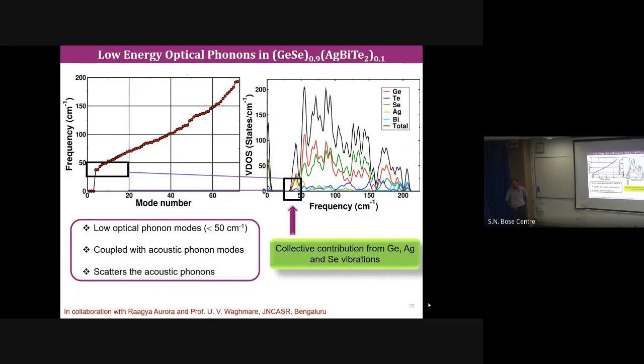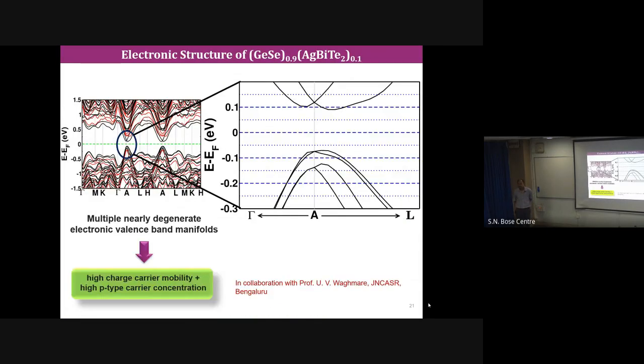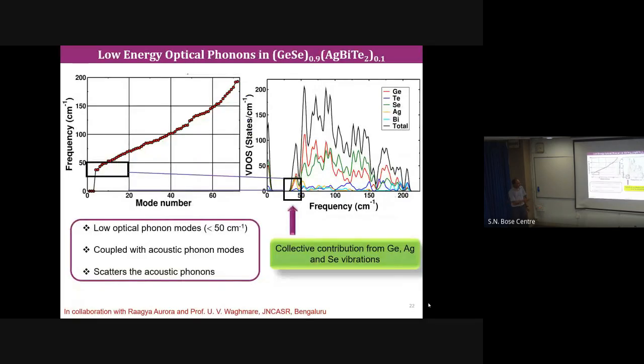Your system is disordered, right? What kind of structure is going? So basically, what you do, you calculate based on the ordered structure, an energy-minimized ordered structure, because the disordered structure is not possible to calculate. And then you check, you do nearest neighbor atom exchange, and again try to minimize the structure. So basically, this is the most minimal, exactly. Yeah. And then we have calculated the gamma point phonon.